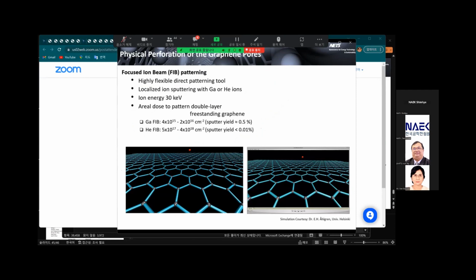On the freestanding membrane, we drill the holes by use of focused ion beam milling. Thanks to the 2D nature of the target material, the drilling mechanism is rather simple. Let me show you here. If bombarding energetic ions happen to hit a carbon atom, the carbon atom gains a part of the kinetic energy. And once the energy gained overcomes the lattice binding energy, the carbon atom can escape via the 2D lattice.